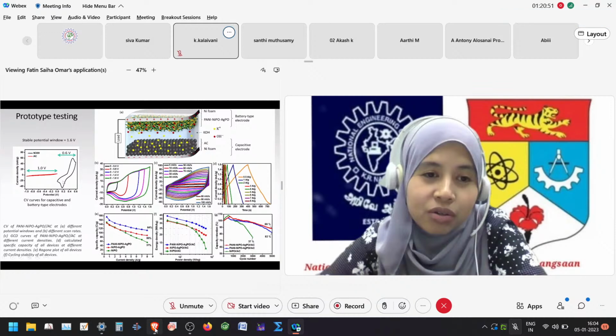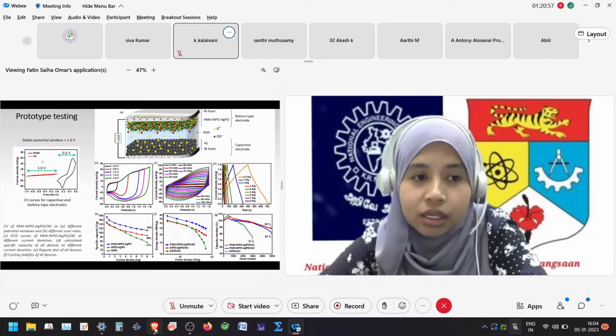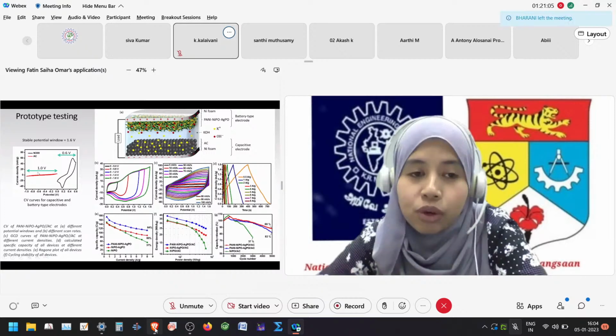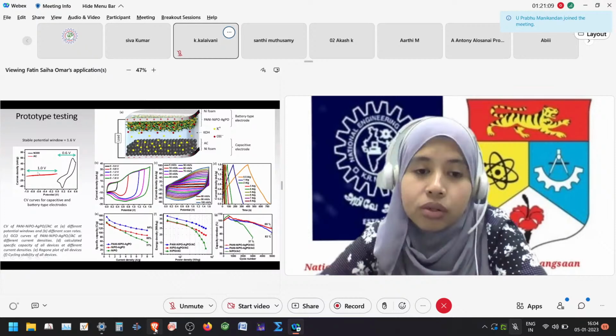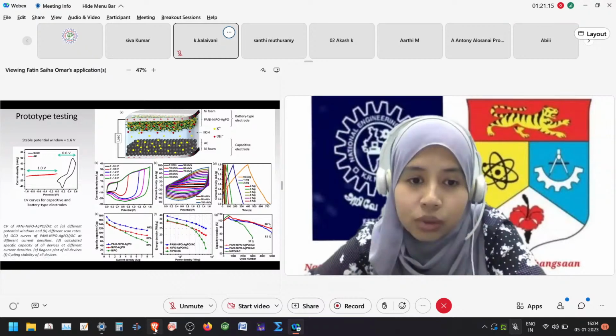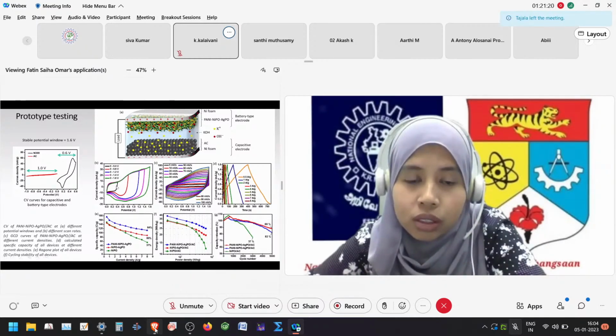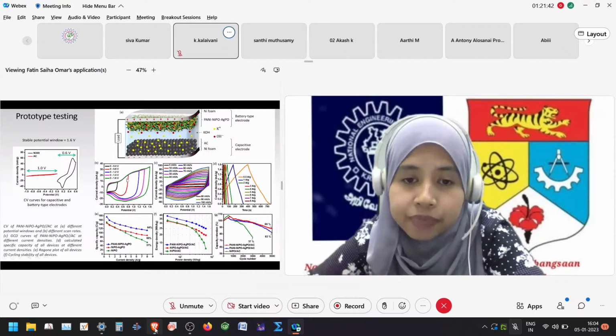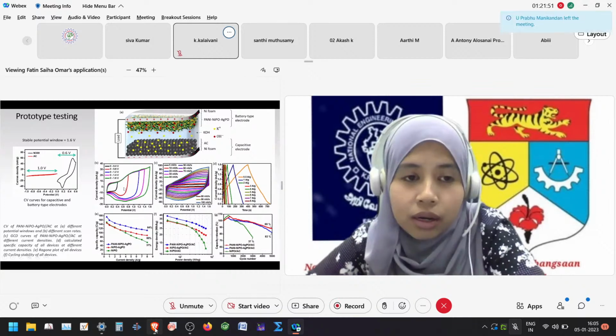So when we add up the voltage of the potential difference of the capacitive electrode and the battery-type electrode, we expect that the potential window of the device is around 1.6 volt. So after combining the two into a device, we try to check the CV profile at various potential windows. This one from 0 to 0.4, this one from 0 to 1.2, 0 to 1.4, 0 to 1.6. Okay, and this is the CV curve of the device. You can see that there is no decomposition happening in this potential window range. So it agrees with the potential window that we summed up from the capacitive electrode and the battery-type electrode.